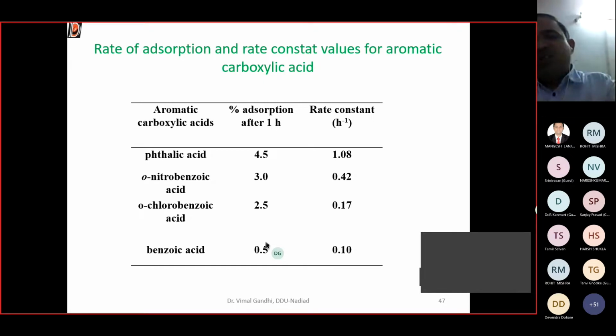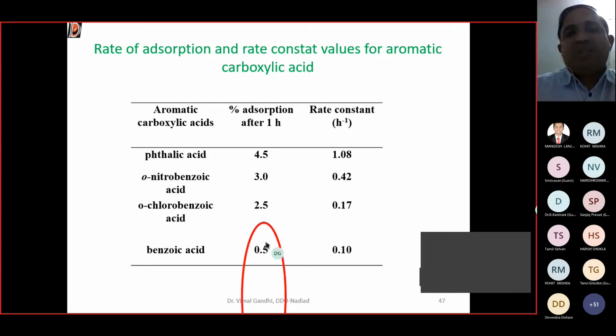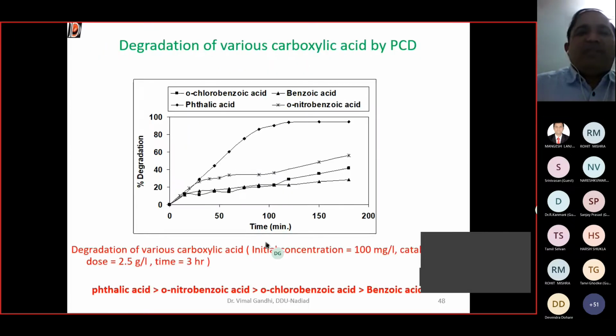We tried to degrade all these 4 aromatic carboxylic acid compounds from synthetic wastewater, and we observed that the removal rate is highest in the case of phthalic acid, followed by orthonitrobenzoic acid, then orthochlorobenzoic acid, and the last one, the least degraded, is benzoic acid. And in the same paper we also proposed a mechanism. I am not going to cover all the details here, but if you have interest, you can go through this publication, which is very good to understand.